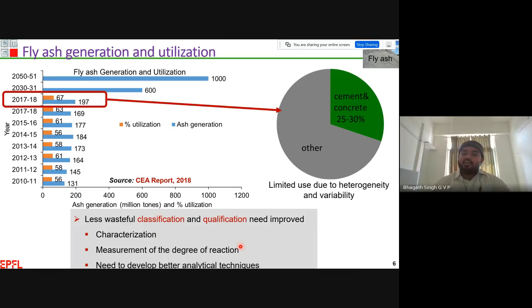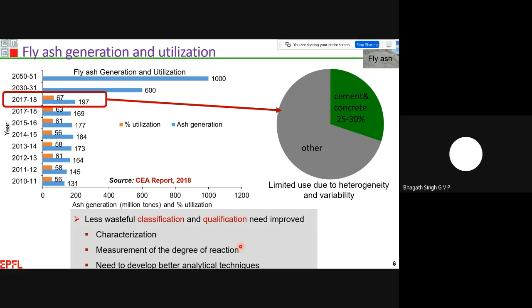And the second point is the measurement of the degree of reaction. If we use fly ash as a binder, over a period of time, how much fly ash is reacting and how much remains non-reactive? How do the dissolution characteristics take place in various environments? Whether the glass present in the fly ash is dissolving or sitting idle in the system. All these things should be understood before we use fly ash in construction applications.